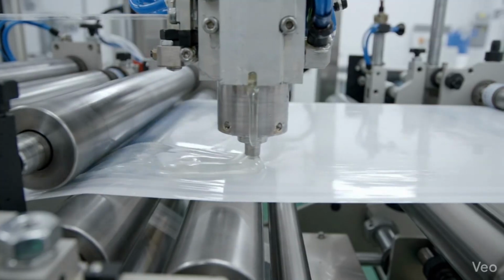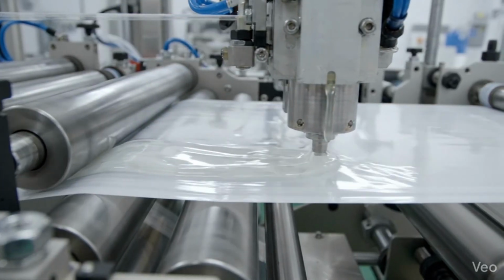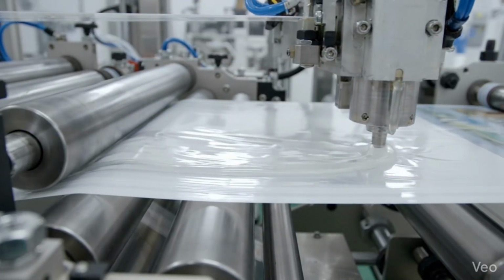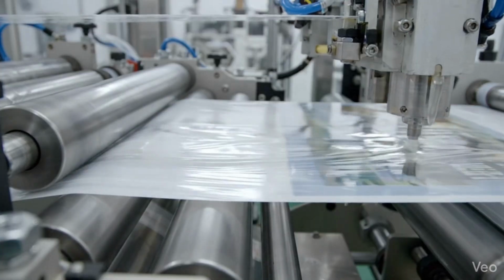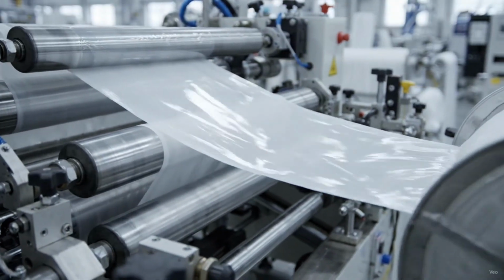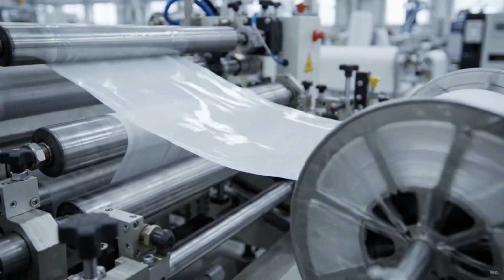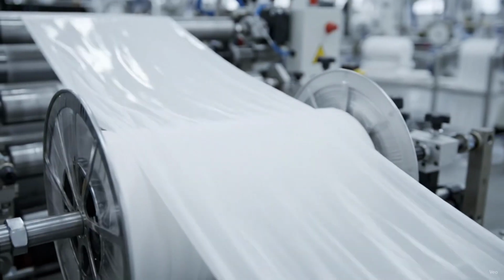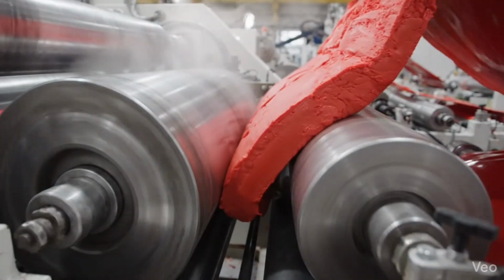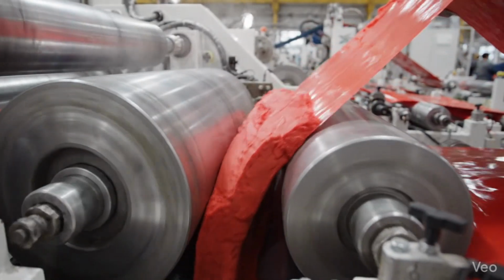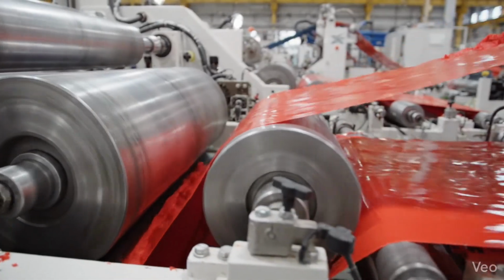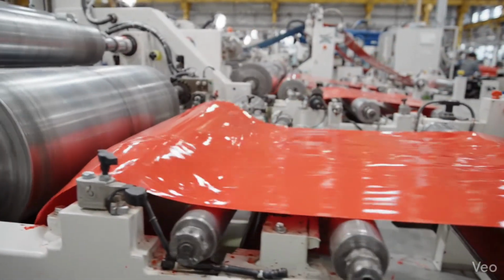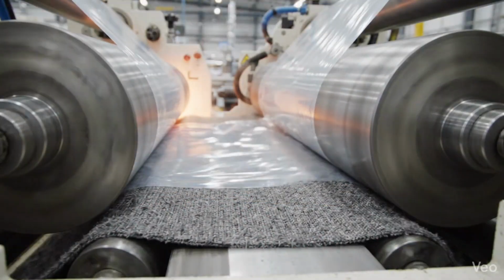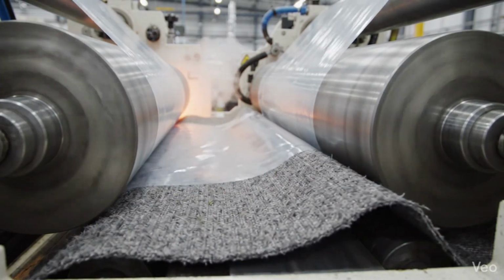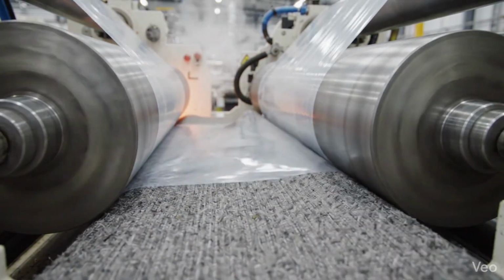In transfer coating, the polymer film is first formed on release paper. The film is then laminated onto fabric, making this method ideal for delicate materials. Calender coating uses heavy rollers to transform polymer compound into a continuous film. Heat and pressure fuse the film directly onto the textile backing.